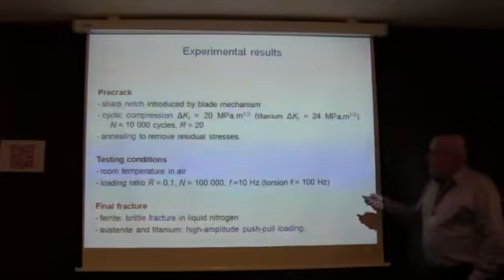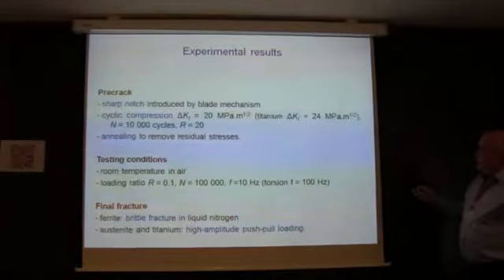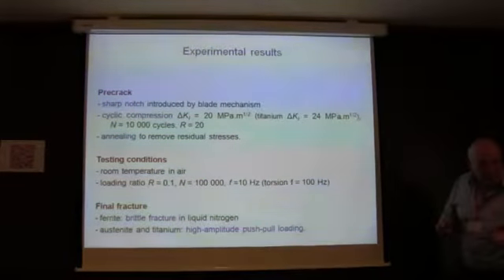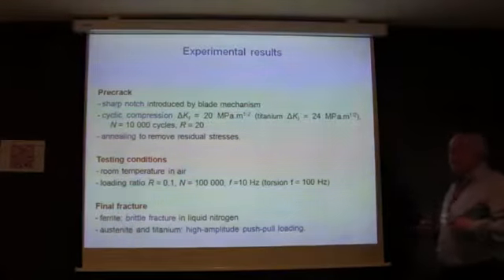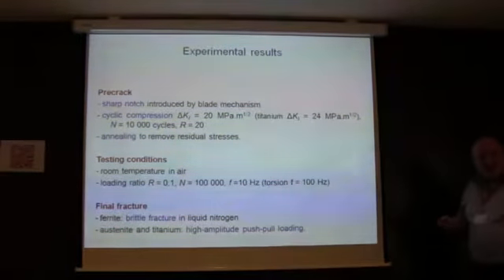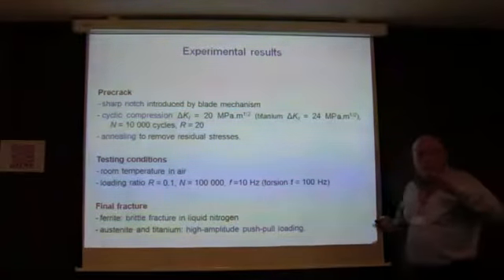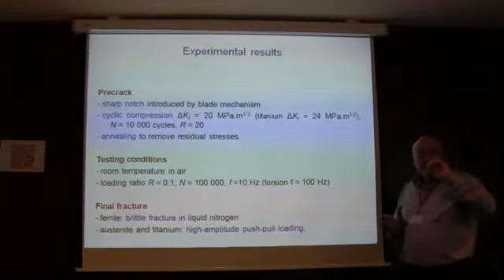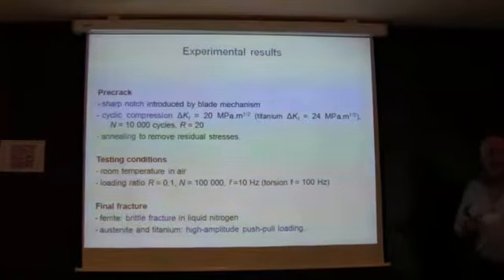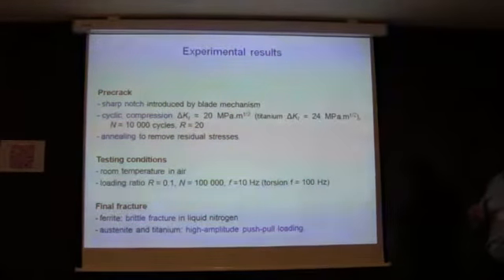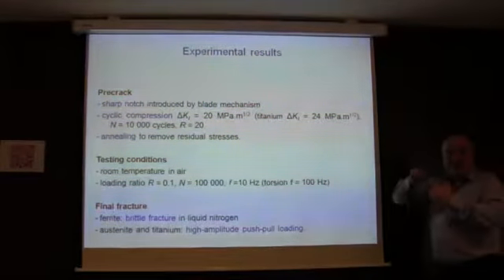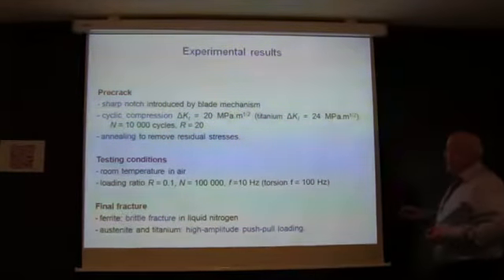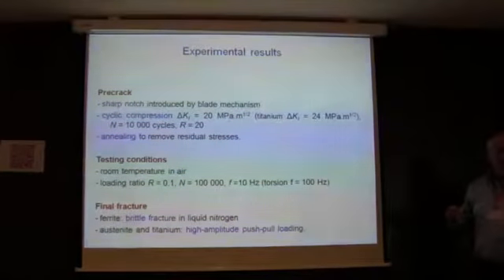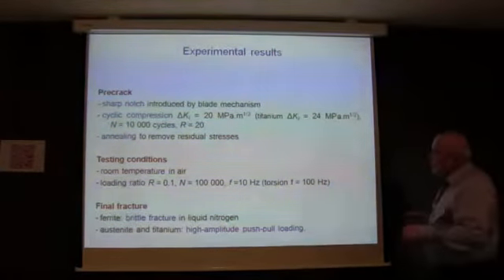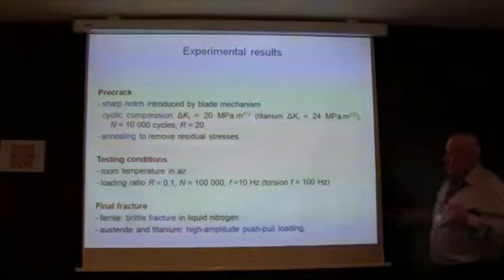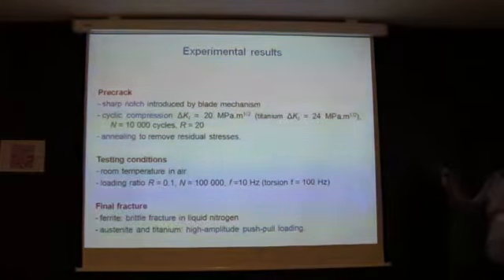So we have a sharp notch introduced by a blade mechanism, and then we applied a complete cyclic compression. And the crack can still propagate, this is well known, but you applied a small residual tensile stress, and these small residuals open the crack. So the crack flanks cannot interact. And then you enable the stresses ahead of the crack to be removed, the residual stresses, and you get an open crack, you can get the thresholds. Okay.